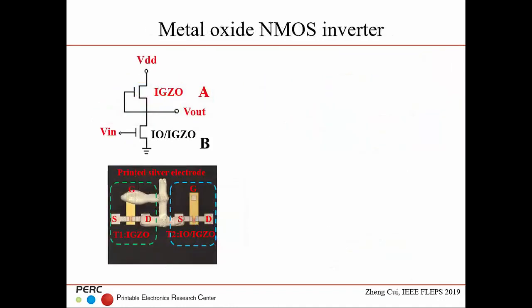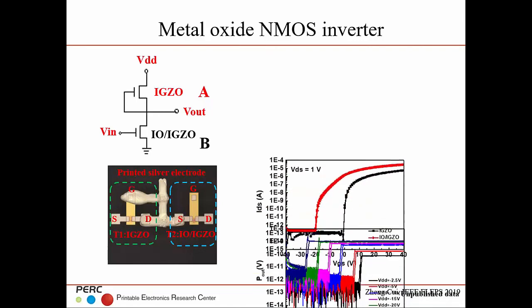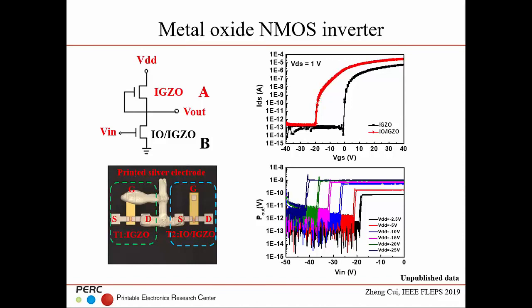But recently, we have work done using the single junction metal oxide and the heterojunction metal oxide. We have both technologies, and this is the way to make the transistor. You can see that these two metal oxides, we use inkjet printing to connect them. And the way they make the NMOS transistor, because they have different characteristics, we use the difference to construct this inverter. And this is showing the power consumption. You can see that in the near off state it is less than a nanowatt, and it's showing that it really can have a very low power consumption of the transistor.